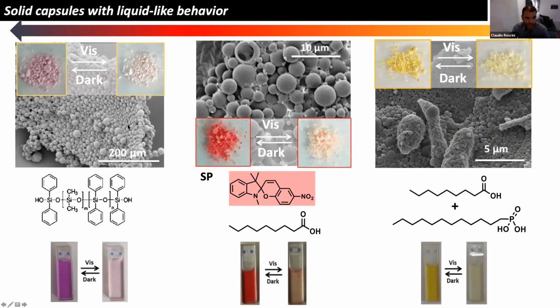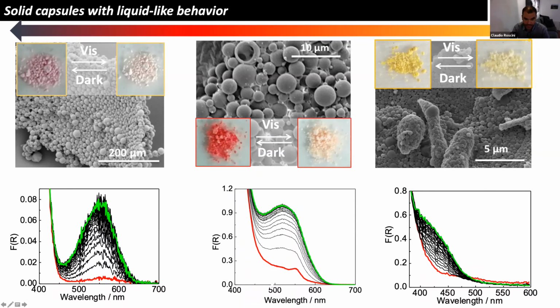We managed to get 3 different pigments containing these 3 different mixtures and our photochromic material, and each capsule reproduces the color that they had in the bulk solution. So once again, the capsule strategy allowed to transfer the liquid behavior to the solid state. And finally, all these capsules showed a reverse photochromism and discolor upon irradiation with visible light.